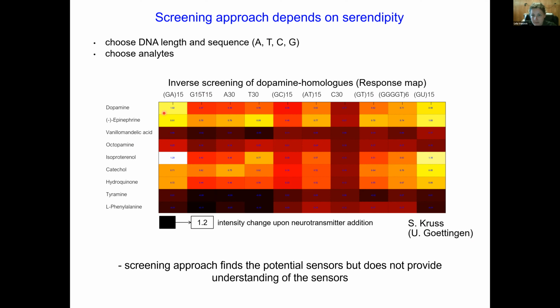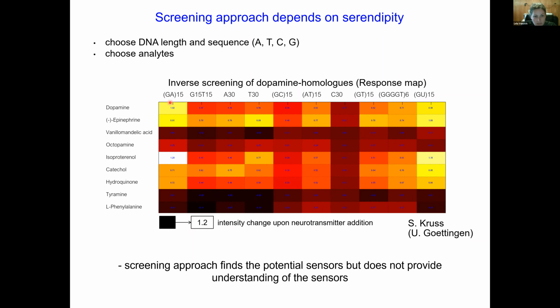And so you can see here an example of an output in experiment. Different types of DNAs were tested, wrapping the nanotubes. Let's say you have here, for example, a sequence of GA15. That just means you have a DNA molecule of 30 nucleotides, which has a repeated pattern of a sequence, GA, GA, GA, GA, 15 times. And so one wraps nanotubes with this type of DNA, and then one checks: if we have a nanotube wrapped by a GA repeat pattern, is it going to give a strong light emission when it's exposed to dopamine? And it is in this case.